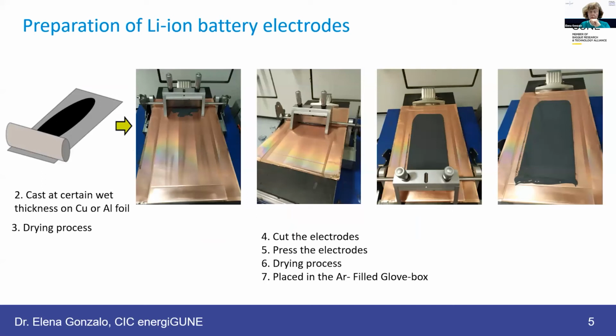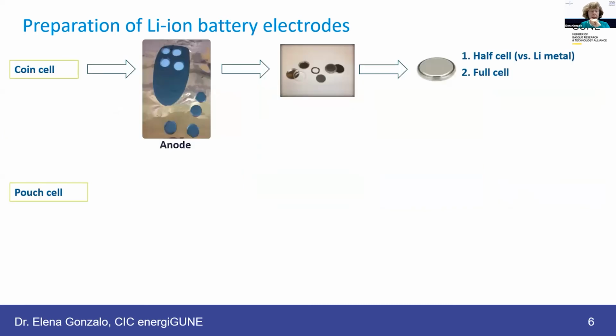The next step was to cast this ink on the copper current collector. Here you have a series of pictures of this A4 size current collector nanostructured by Lasea that was done with the help of a blade in a vacuum table. And we were able to control the wet thickness of the electrode. So this is our final result, the anode electrode. And what we had to do after that was cut the electrodes, press them and dry them to be assembled in a cell. Which were the two configurations we were playing with?